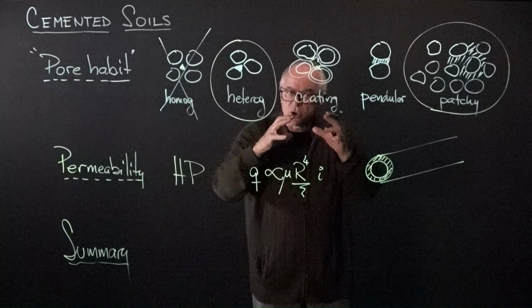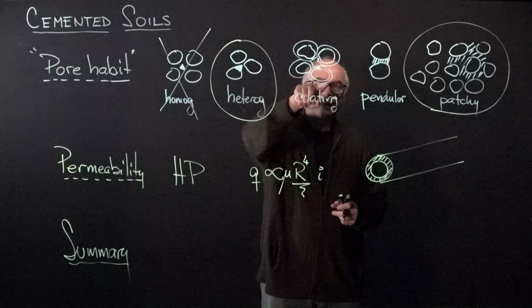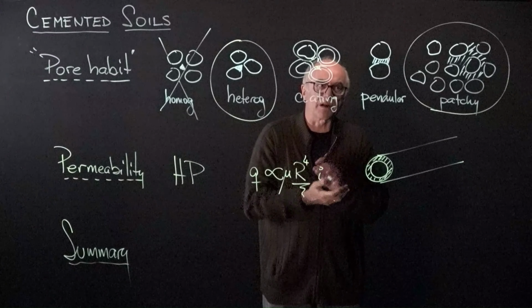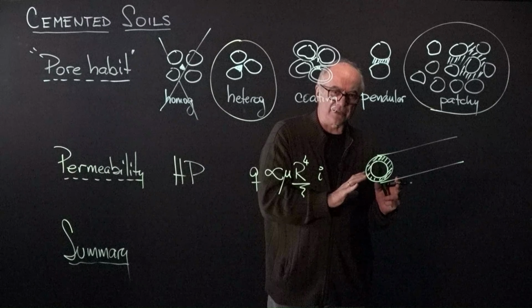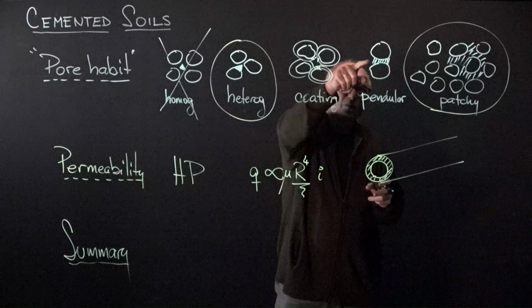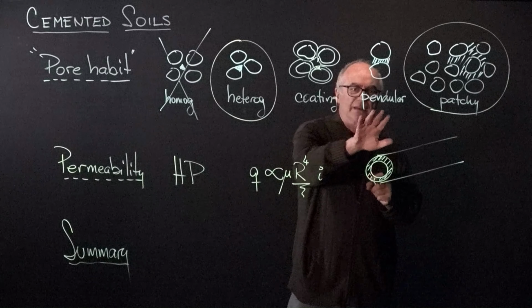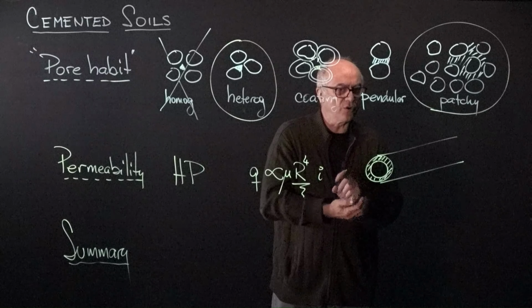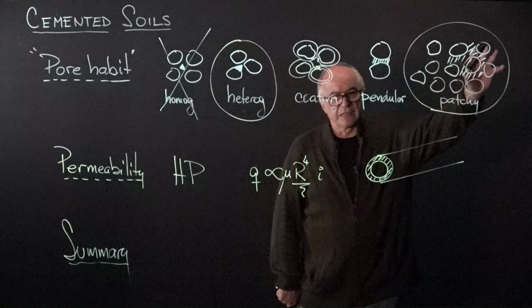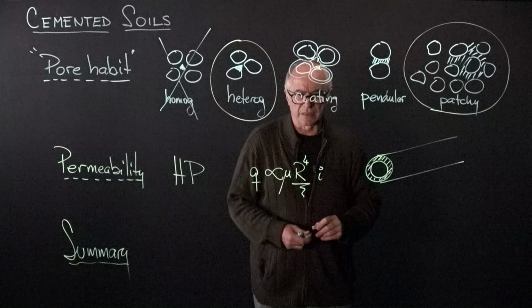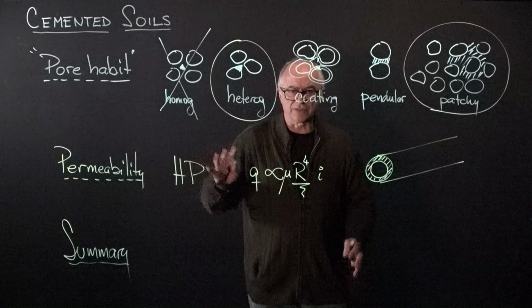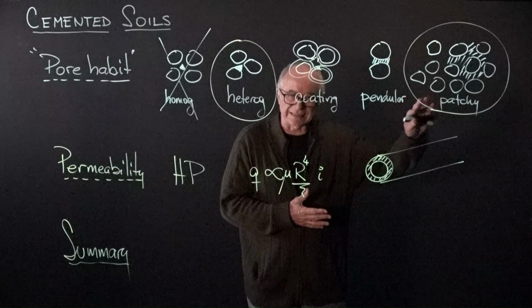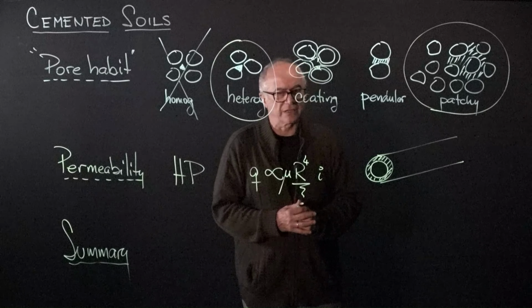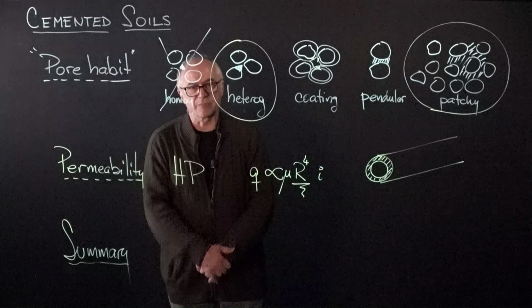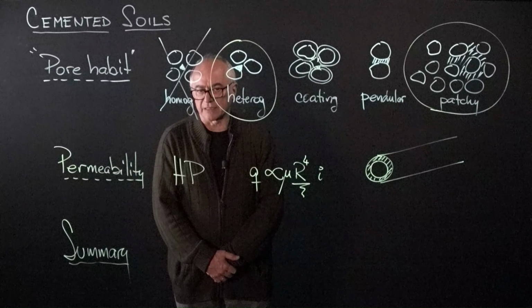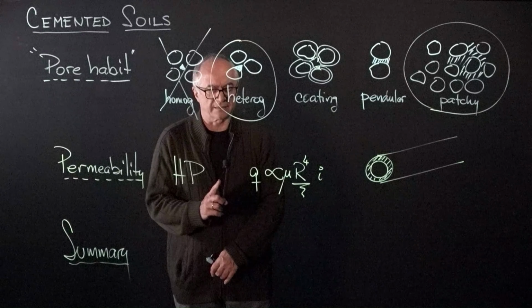But if there were biofilms coating the particle, it is very likely that it may have formed a coating surface around each particle. If it formed under unsaturated conditions, as the soil began drying and all the species were concentrated at the contact where precipitation took place, it's going to be a pendular type of cementation, which is the most impactful. And because of Ostwald ripening, it may tend to evolve towards a patchy structure. It affects small strain, dilation, therefore the evolution towards a critical asymptotic state, both in terms of strength and in terms of void ratio versus confinement, as well as permeability. Cementation is best detected in the field using shear wave velocity. Don't miss it. It can really affect the design.